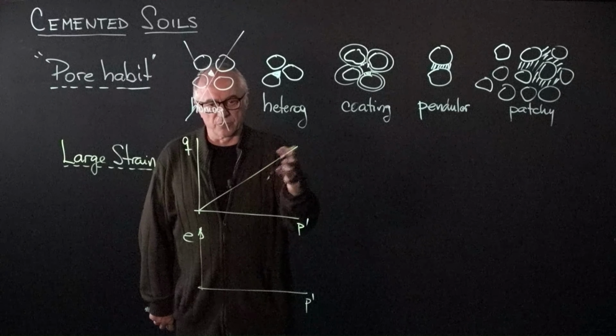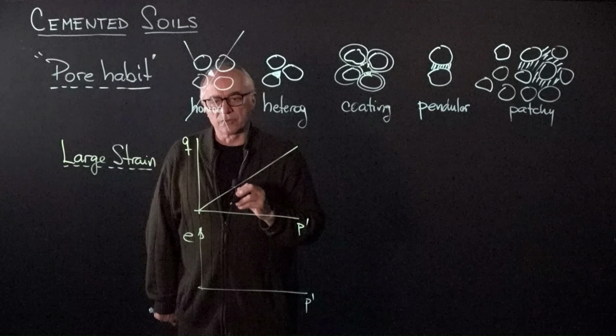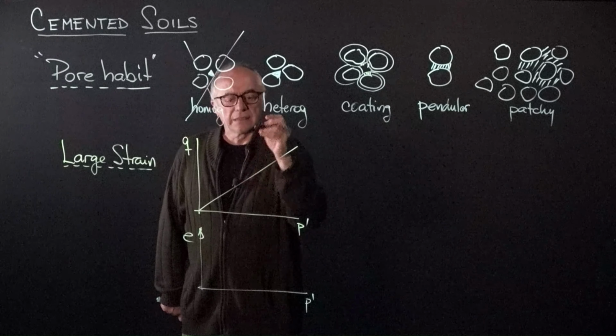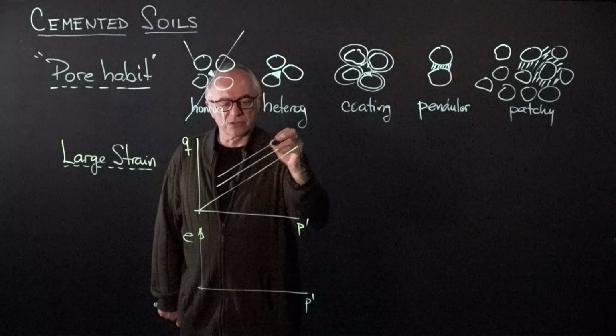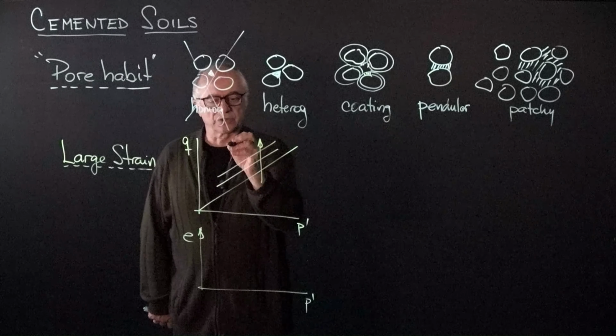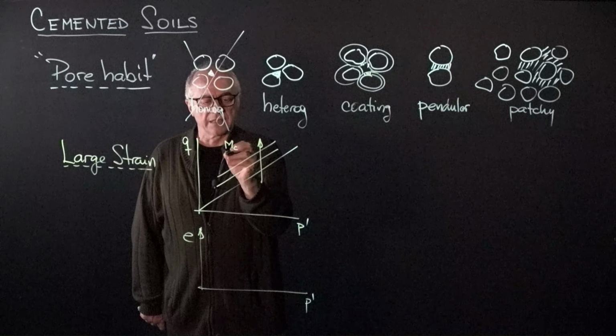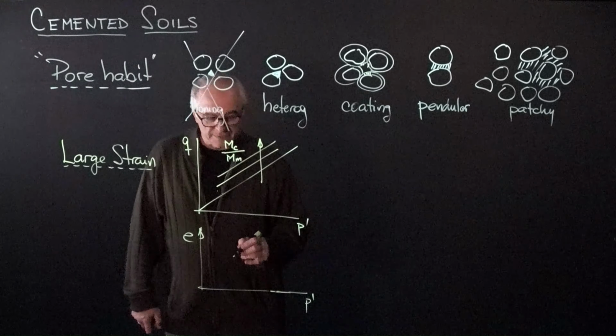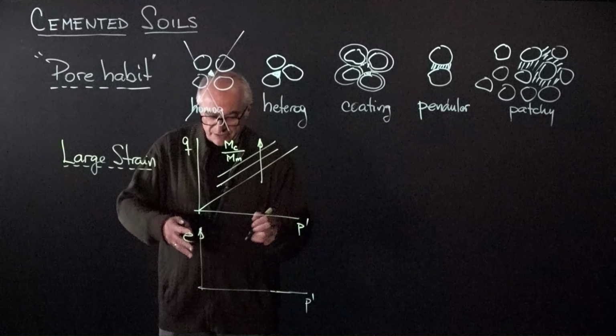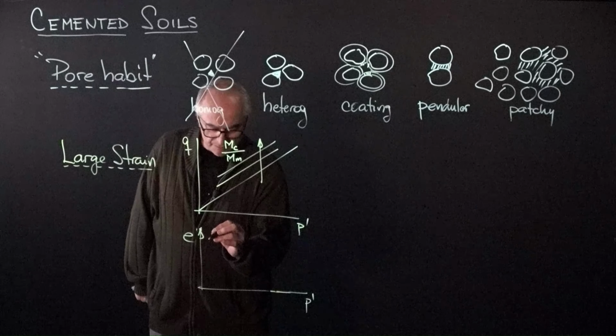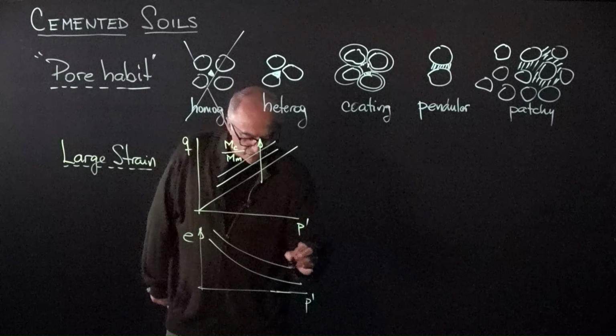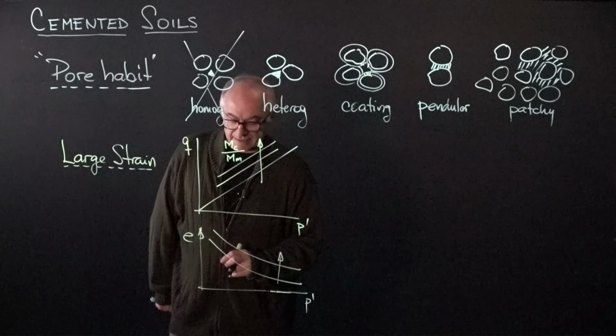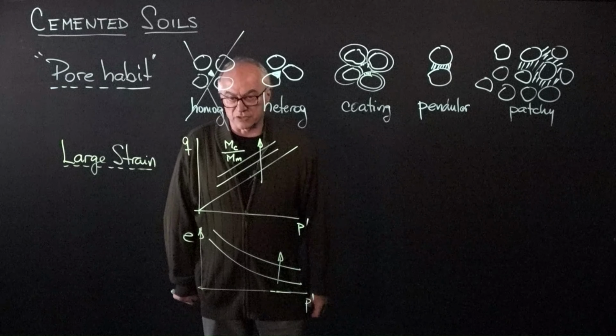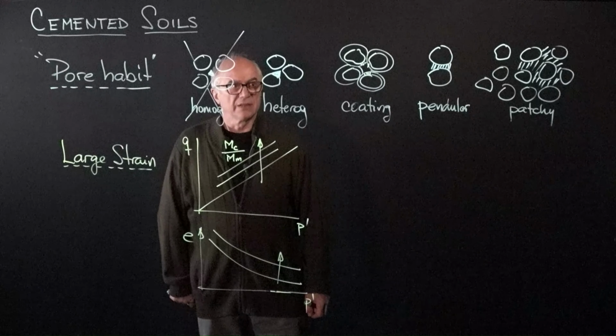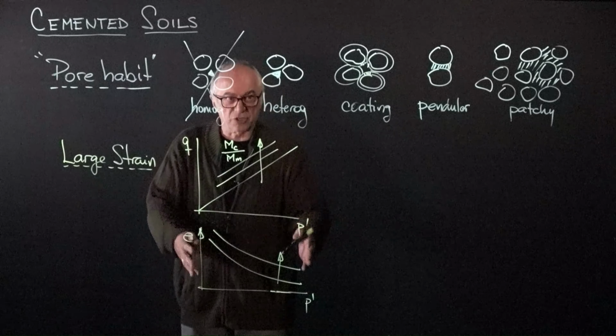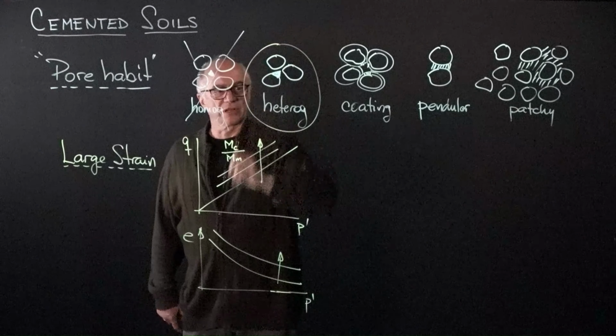So this requires quite a lot of cementation, but if we do that, in the QP space, this would be the slope of the Mohr-Coulomb curve, now in QP, for the uncemented soils. And as we add cementation, this is going to move the lines up. So this is when I increase the mass of cement with respect to the mass of minerals. In the EP prime, and please notice that I have void ratio moving up, this would be also a shift upwards due to the fact that we have cementation with significant dilation. So this is the case, the one I'm showing here, for heterogeneous pore habit.